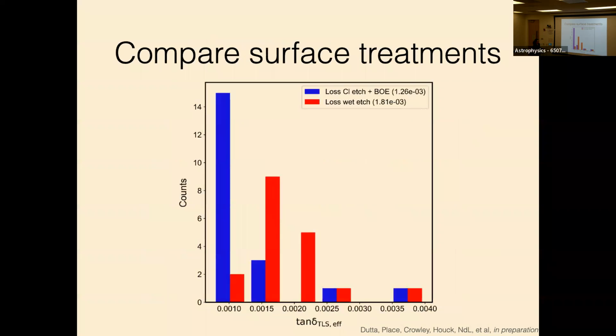Okay, and this is just another graphical representation of this. You can just make a histogram of these apparent loss tangents and compare surface treatments. And we see that we do actually get this big improvement, about a factor of 2, when we do this final buffered oxide etch dip.